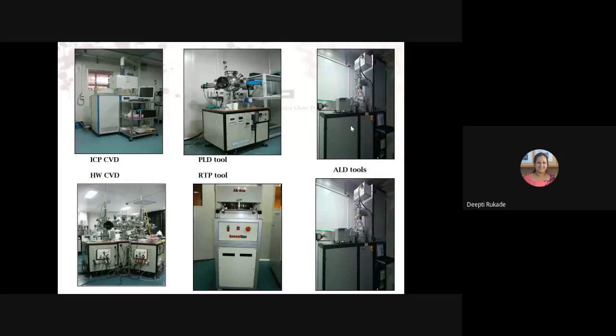Then after that, we ensure that whatever precursor we have sent initially is purged out. So to ensure that, we purge in an inert gas, mostly argon, and ensure that the remaining precursor, which was earlier purged in, moves out. Then we send the second cycle. So ALD basically gets its deposition in a series of cycles, which is called a half cycle in the first part and a complete cycle. So there are these cycles of ALD, which give you one monolayer deposition at a time, and you get a very high quality of your thin films. So at IIT Bombay, we have a few materials that I'll show in my next slide, which we deposit, mostly TiO2, or we can go Al2O3.